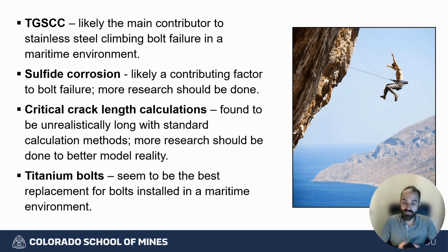In conclusion, we found that transgranular chloride stress corrosion cracking was likely the main contributing factor to the failure of stainless steel climbing bolts in a maritime environment. In addition, sulfide corrosion could have been a contributing factor, but more research needs to be done. Our calculations for critical crack length were found to be lacking when using standard methods. We found critical crack lengths that are unreasonably high, and so more research should be done to better model theory to reality. Finally, we found that using titanium bolts is likely the best solution to prevent stress corrosion cracking in a maritime environment.